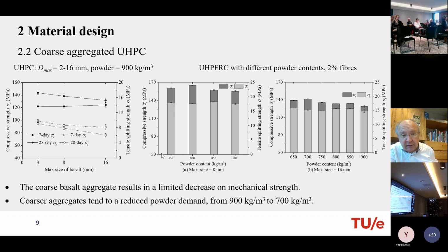Also the powder content decreases, there's less powder needed when you have more aggregates in your mix. And we saw we could reduce, by increasing the aggregate size and aggregate content, the powder demand from 900 kilograms to 700 kilograms. And the 700 kilograms, as we have seen, consist, let's say, for half of cement only. So actually we are making a high performance concrete with quite normal cement contents already, which is very interesting, I think. Let's see the next slide.